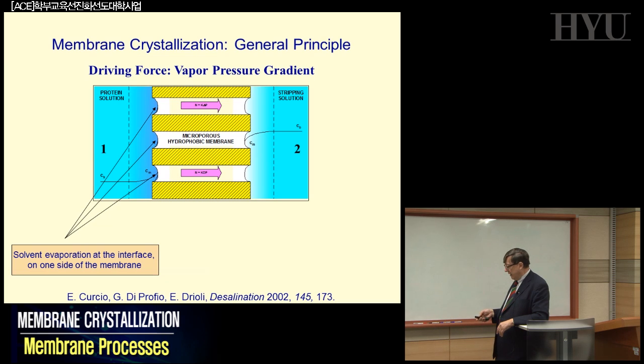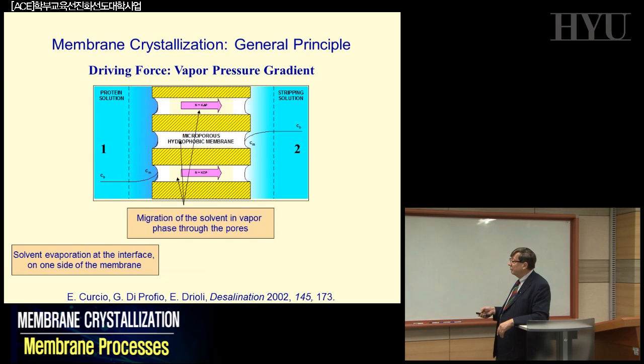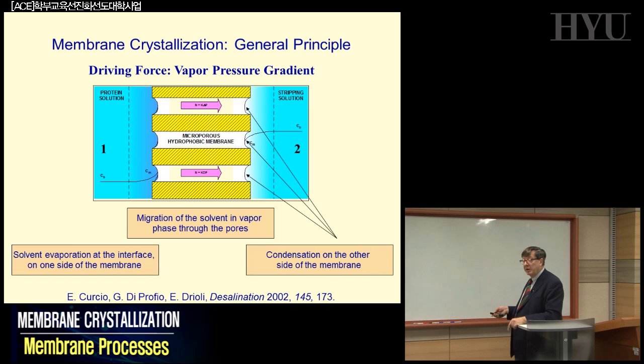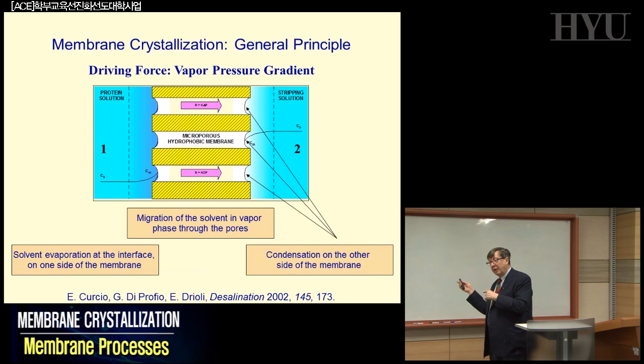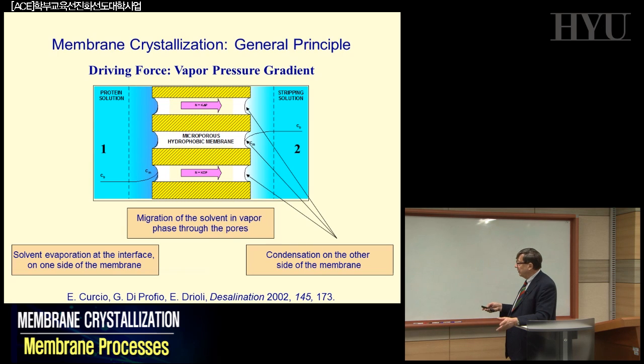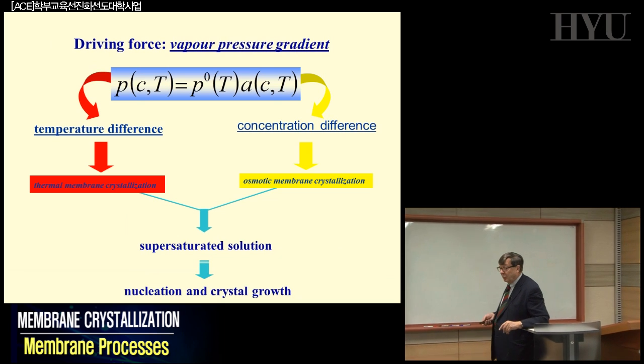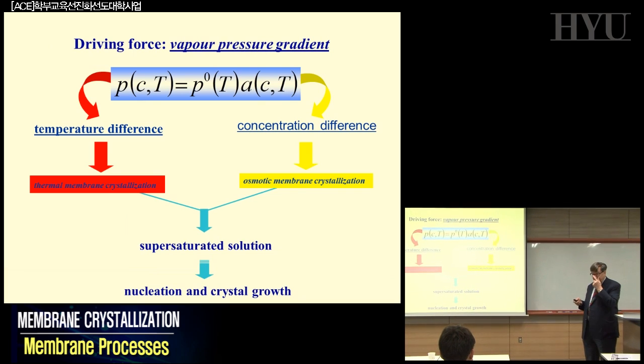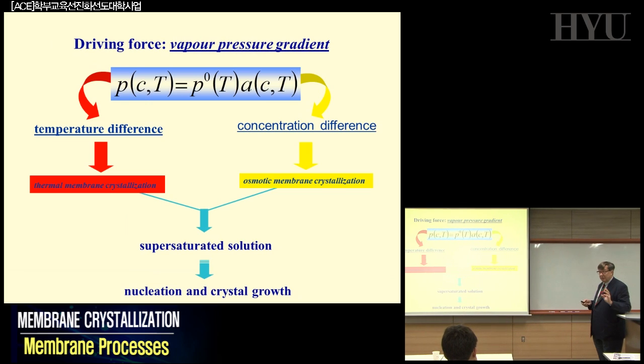Solvent evaporation at the interface on one side of the membrane, and migration of the solvent in vapor phase through the pores of the microporous hydrophobic membrane that we have been utilizing, and condensation on the other side of the membrane following one of the different configurations that we discussed last time: direct contact membrane distillation, vacuum membrane distillation, air gap membrane distillation, sweeping gas. For the moment, at least, we have these 4 different options, but as you can see, the mechanism was exactly the same as membrane distillation, except that you don't stop at a certain level of water production. You want to concentrate as much as possible. In doing this, you must be careful, because we know that if we concentrate too much, we can have fouling phenomena, and that will be one of the major points to keep under control.